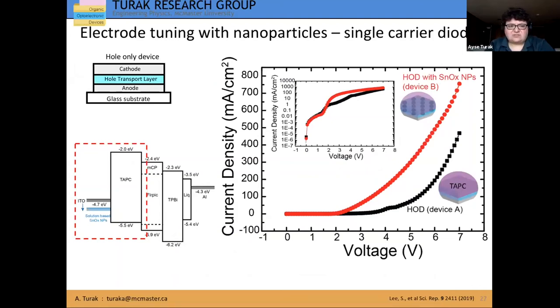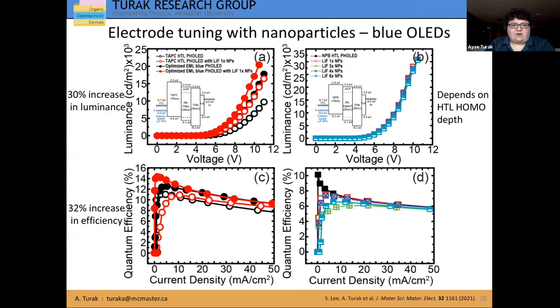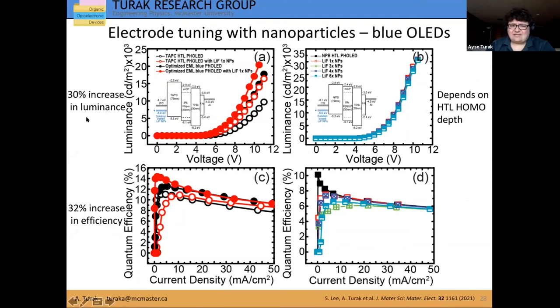If we looked at single carrier diodes — in this case we were making tin oxide nanoparticles — we can see a significant increase in the amount of hole injection as a result of having this nanoparticle array on the surface. And that carries over if you're going from an OPV type device to single carrier diodes into OLEDs. We were making blue OLEDs where we introduced nanoparticles — in this case lithium fluoride, but we can also do it with tin oxide and other kinds of oxide materials. And purely by introducing these nanoparticle arrays, we can see significant increases in luminance and in efficiency for a wide variety of materials, particularly materials that have very deep HOMO levels that are hard to access by other types of interfacial parameters.